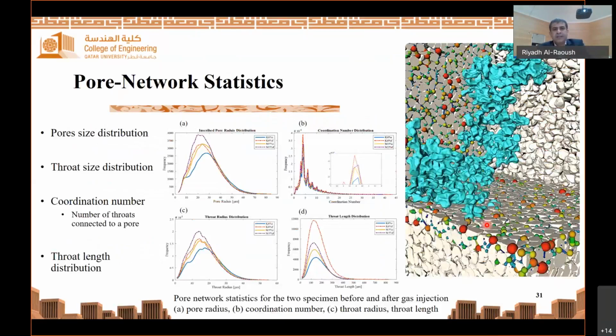This slide here shows an example of the outcome of pore network extraction for a sample of unconsolidated porous media. So we see here the pore size distribution. You can see here the throat size distribution. You can see here the coordination number, which is the number of throats connected to a pore. And what you see here is the throat length distribution. And these distributions, as I mentioned, are used as input for pore network modeling approaches.